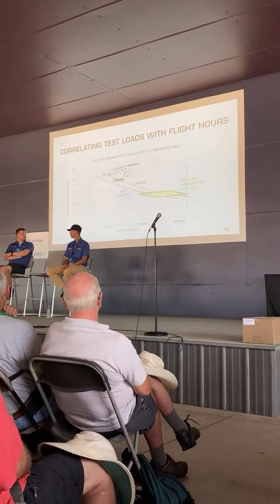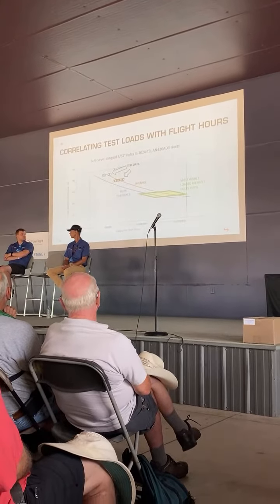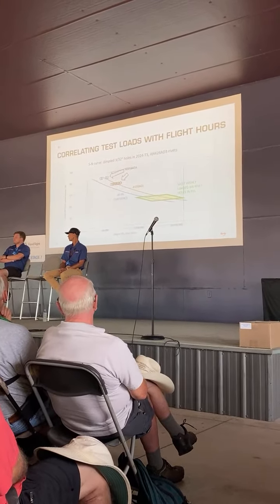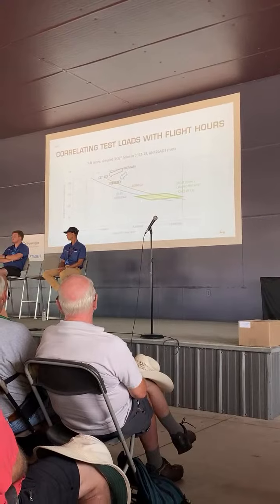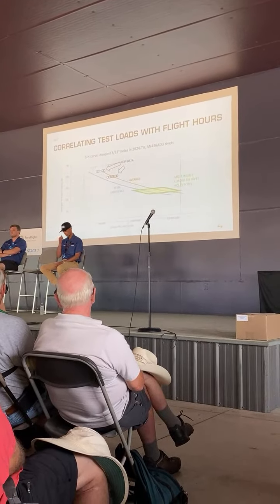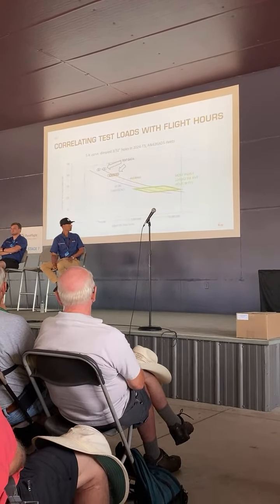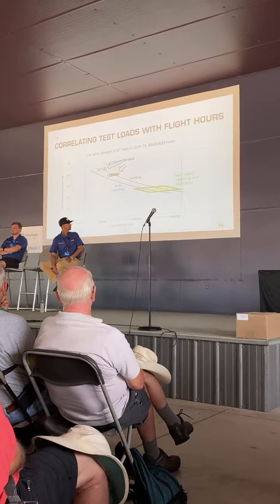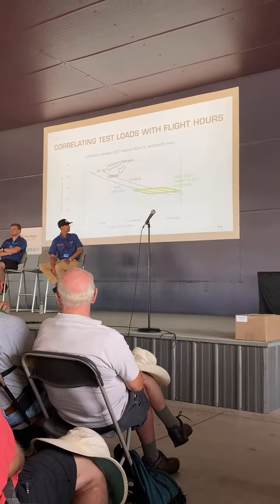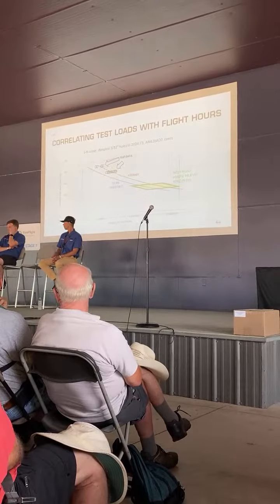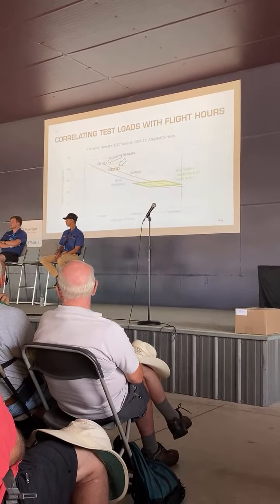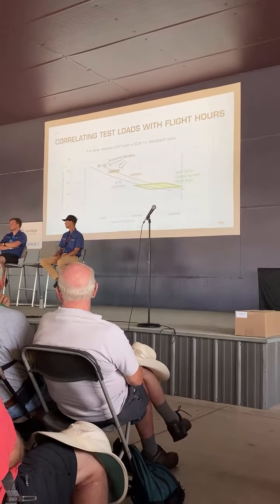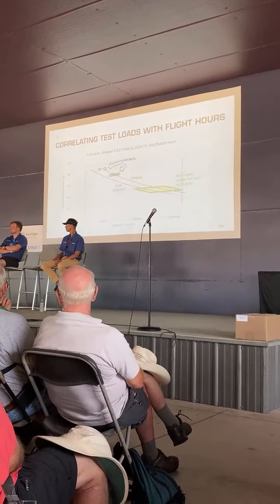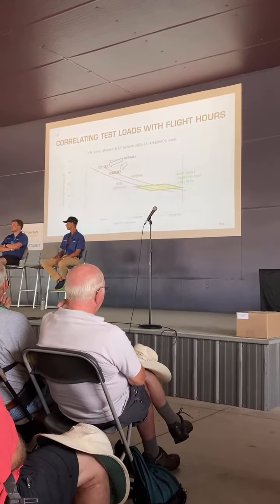And as you can see, here's our test coupons, which are running at about 150,000 limit cycles. And these tests out here, if you equated the life there, it would be between 1 million and 10 million limit cycles. So that would be like an RV-12 lasting over 1 million hours at that. But we have to also consider the aerobatic loads, which has a significant reduction.